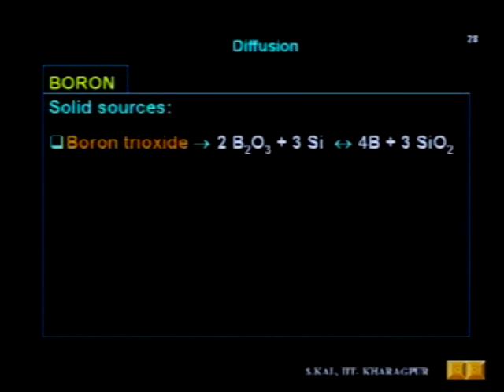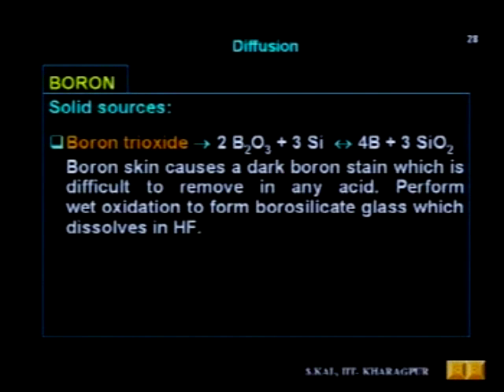And boron has three sources, namely solid source, liquid source, and gaseous source. In solid source, we found boron trioxide is a material which is used frequently, that is B2O3, and the reaction is 2 B2O3 plus 3 Si gives 4 B plus 3 SiO2 at high temperature. Boron trioxide is a powdered, solid material. If you keep it in a platinum crucible inside the diffusion furnace, and flow some carrier gas over B2O3, that gas will carry some of the B2O3, and at high temperature it will come in contact with silicon and react with silicon, forming boron as well as silicon dioxide,